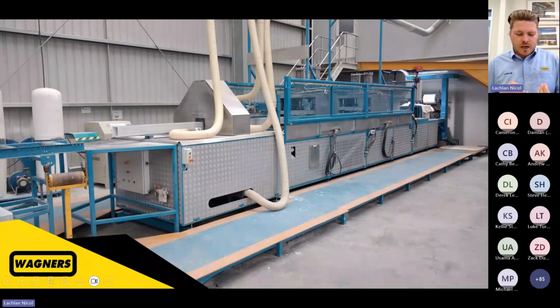Some of our key points of difference is our glass to resin ratio. So we have a unique method of applying the glass around a centre mandrel called pull winding, as well as our injection die. So typically, normal pultrusion processes would require a bath and glass mats, and that also means a lot higher resin ratio, which, as I mentioned before, doesn't provide you any real strength. It just holds all the glass rovings, which do provide the strength in the material. So our glass to resin ratio is about 77%, whereas typical pultrusion processes are about 50 to 55%.